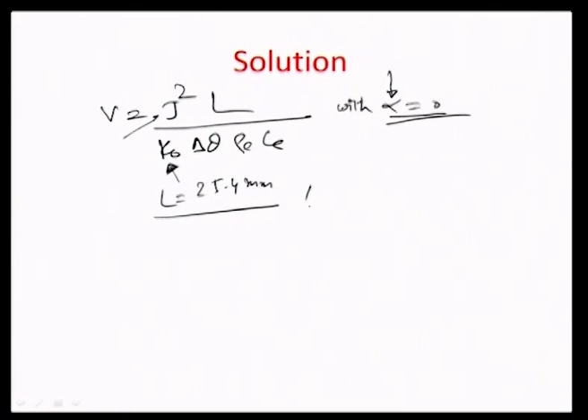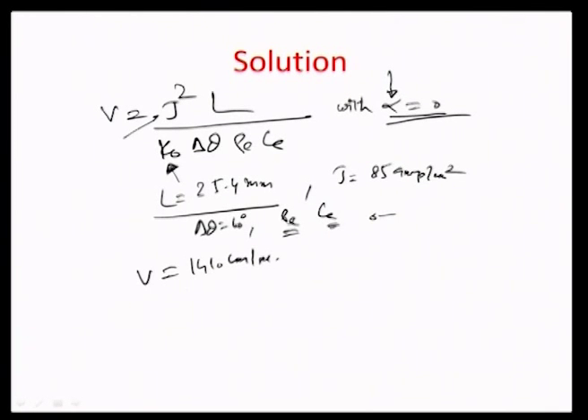The J value, of course, has been found in the earlier step as 85 amps per centimeter square, delta theta is 60 degrees, and rho e and C e, the density of the electrolyte and the specific heat capacity of the electrolyte, have their own values which are given in the question. The velocity of design here can be found out to be 1410 centimeter per second. Okay. So, that is what would be the typical range of these velocities of electrolytes.